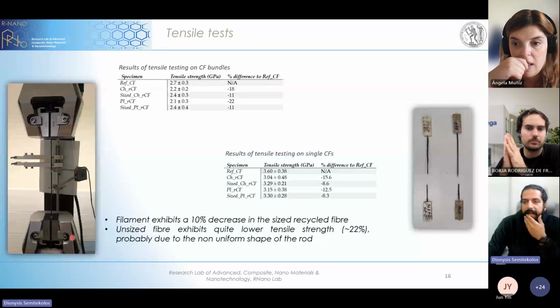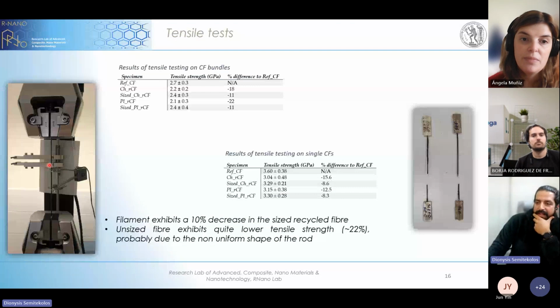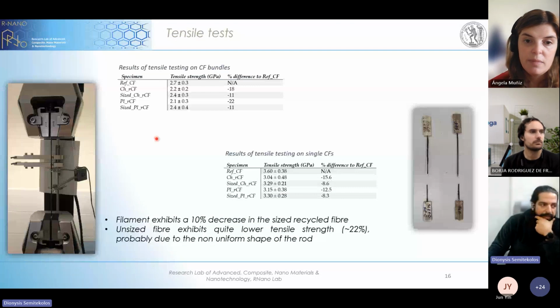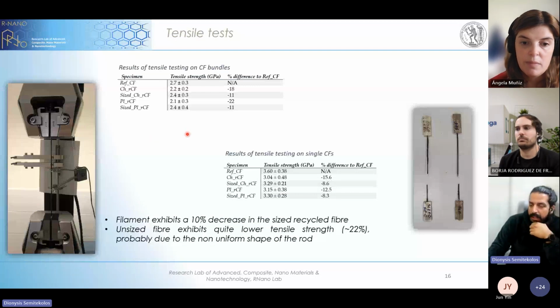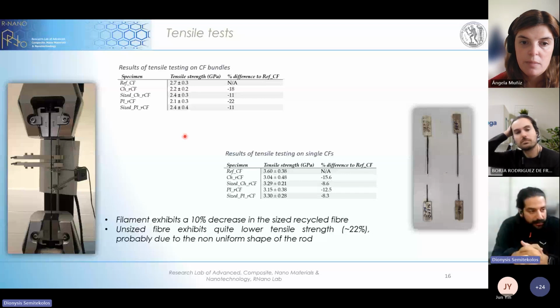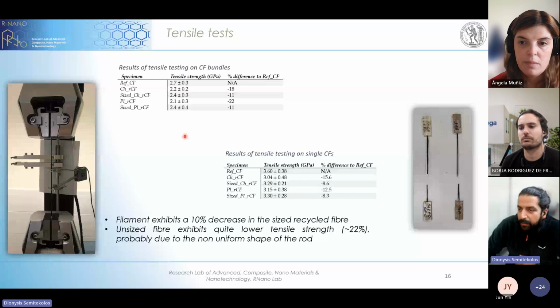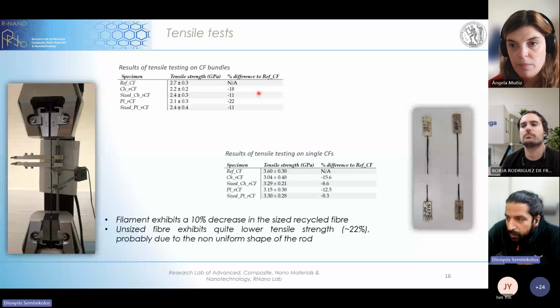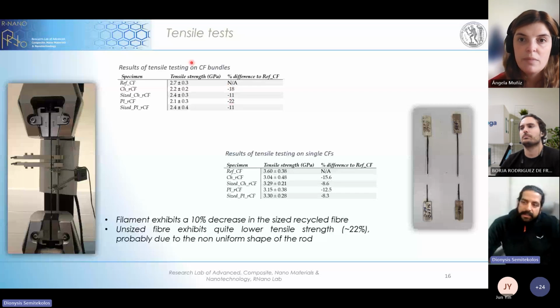And in the end, I wanted to show you some of the tensile tests that we have done until now. For the tensile properties, ideally, we wanted them to remain unaffected after the solvolysis. However, we see here, when compared to the reference sample, a decrease of approximately 18 to 20%. And these are tensile tests on carbon fiber bundles. We also did tests on single carbon fibers.